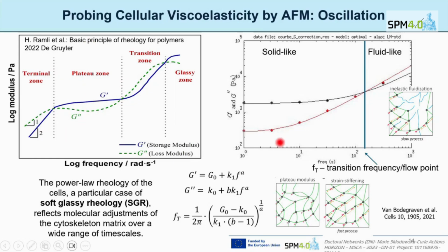this result resembles the behavior of a polymer network, which is presented here. So at low frequencies, we observe that the elastic modulus, the storage modulus, is larger than the loss modulus, so the cell is more solid. The behavior of the polymer is more solid-like.